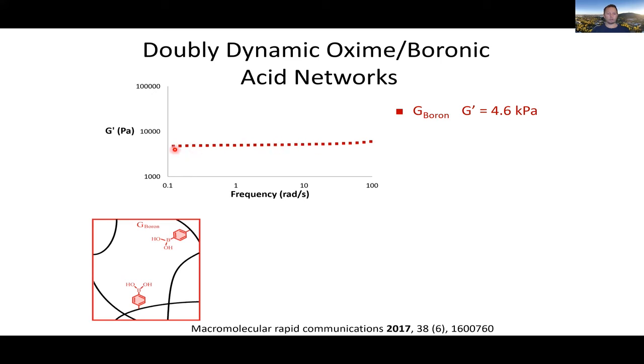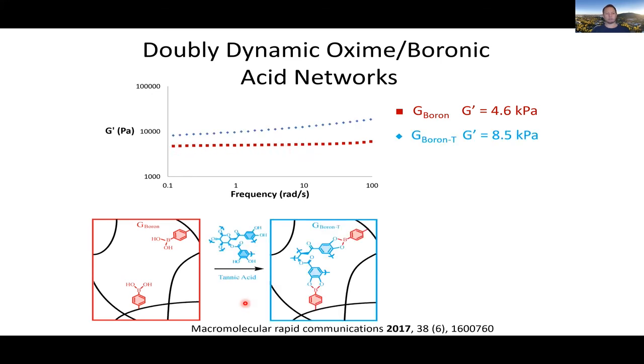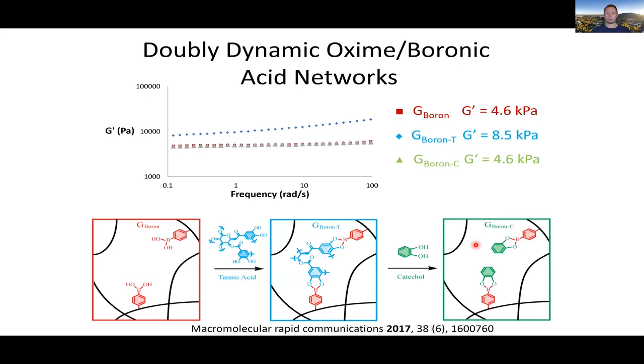We have a certain property here. So we have a gel. It's a fairly soft gel. What we can do is cross-link a second time with this different network, and we can have a second dynamic cross-link. These boronic acids are also a dynamic covalent chemistry, so this can reverse back as well. If we reverse that by adding a catechol into this system, we can go back to its original properties. So we have a network, we cross-link that network and it makes it harder. It goes from this red line, red dots, to the blue. So it goes from soft to hard, and then we can break that second network with the catechol, and it goes back to soft again here.